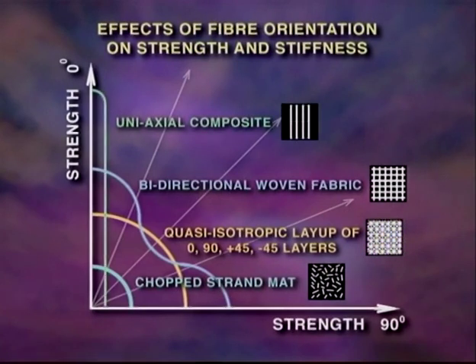If all the fibres are aligned in the one direction, then the strength in that direction will be more than twice that of the bidirectional woven cloth. It will have very poor strength in all other directions. If stiffness instead of strength were plotted, the graphs would be very similar.